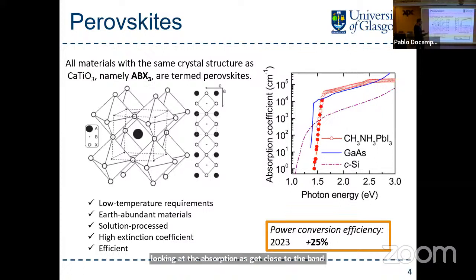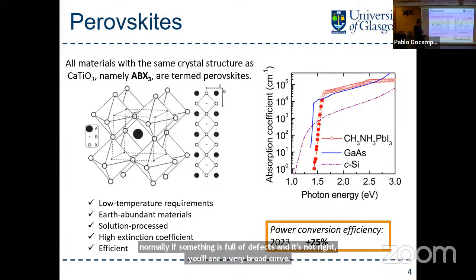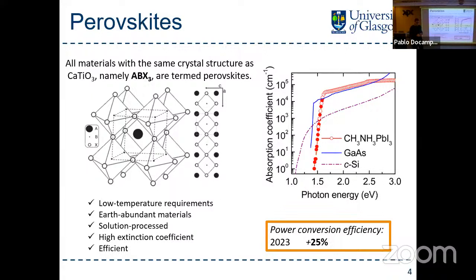So the sharper this slope is, it means the fewer defects it has, or at least those defects do not absorb light. It's a measure of material quality. Normally, if something is full of defects and it's not great, you'll see a very broad curve. What you see here is that the perovskite absorption is not that different from gallium arsenide, which tells you that these materials crystallize in very high quality from these inks. So it's very interesting from that point of view. It's a very defect tolerant system. And currently we're at 25, almost, I think it's 26% now, efficiencies, which competes quite well with silicon. I should say in a small area. We're not competing in the big area.